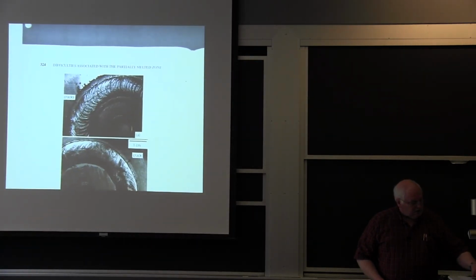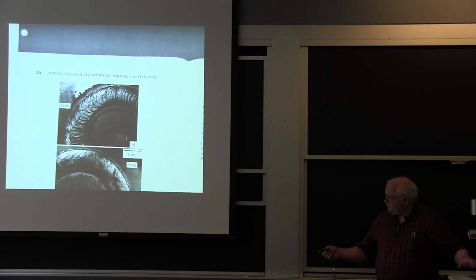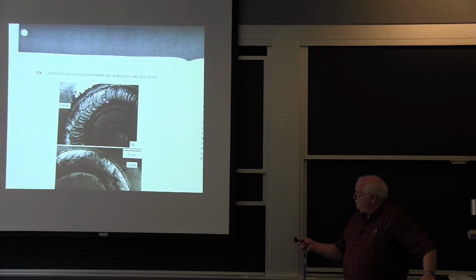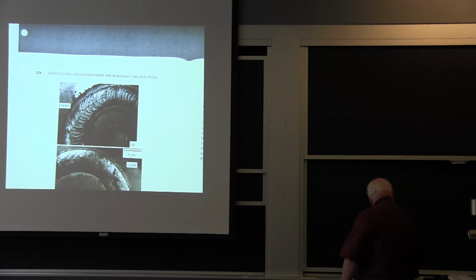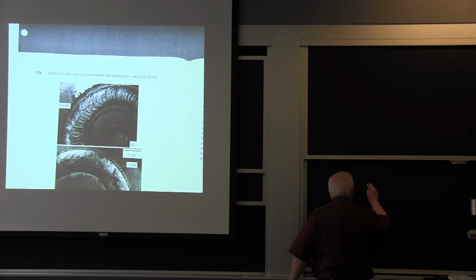To give you an idea of some of the cracking you get, this comes out of Sindo Kou's book. The first one is 6061, where they used 1100 filler metal, and I'll explain why this is a problem. The reason it's a problem is 1100 filler metal is nearly pure aluminum, and the 6061 is highly alloyed as a precipitation hardenable alloy. I don't have a picture of this close by.